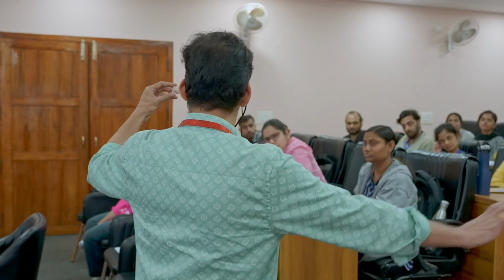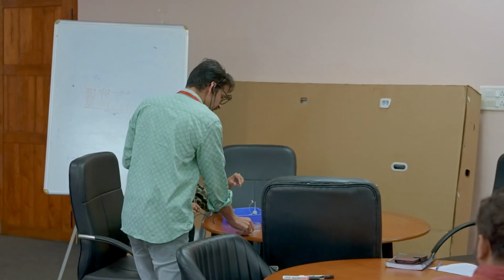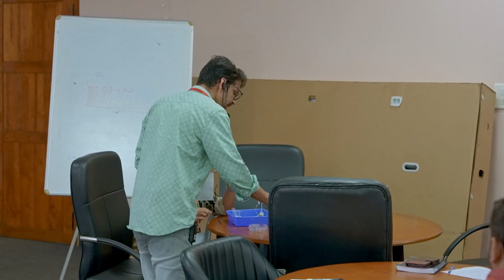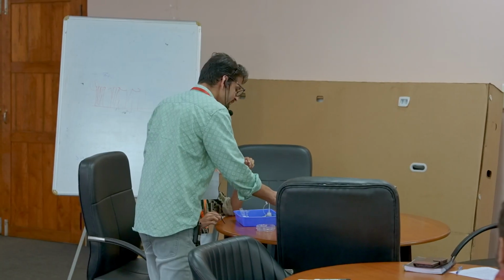Okay. So you can see a droplet over it. As you see, it slides. And it has a low contact angle, but it slides well at a very low tilt angle, right? You remember the previous case? The pristine PDMS had to go almost 90 degrees to take out the drop, and his structured surface was not able to do it even when tilted. Now, even at like 10 degrees, 20 degrees, it's not the optimized situation, but it works, right? It slides, right? You agree with me, or am I doing any manipulation?